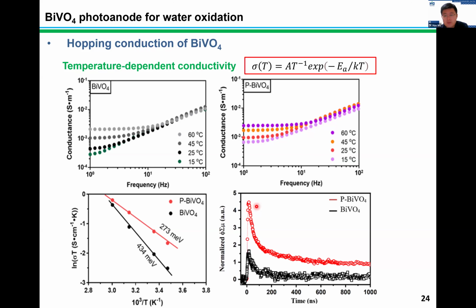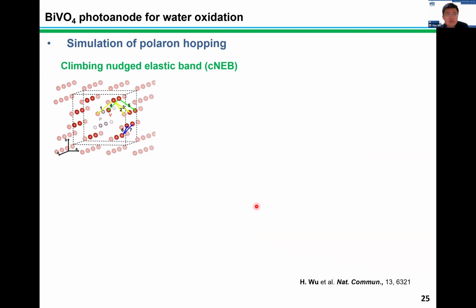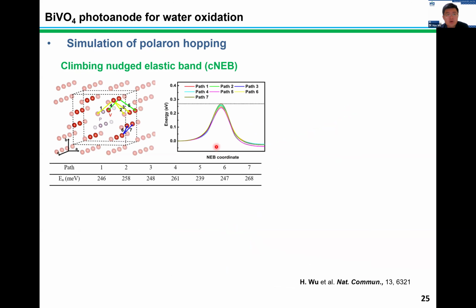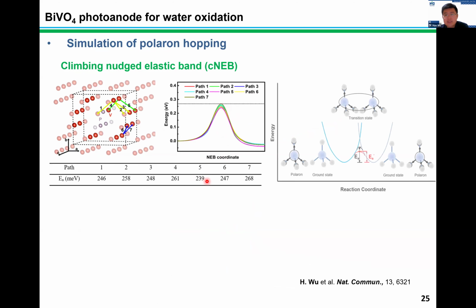Upon knowing this from the experiments, we also did a theoretical study of the polaron hopping behavior within our systems, and we found that upon the phosphorus doping, we changed the polaron hopping behavior within the bismuth vanadate and reduced the hopping barriers, with the lowest activation energy going to 239 milli-electron volts compared to that of the 268 of the pristine bismuth vanadate. And it suggests that it will require less activation energy for the polaron to hop from one reaction coordinate to the next. So it can promote the polaron movement.